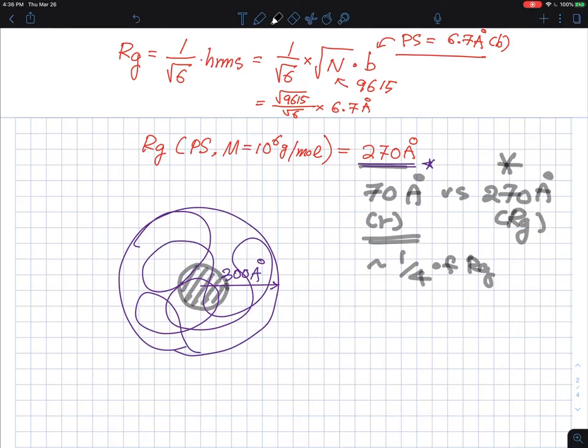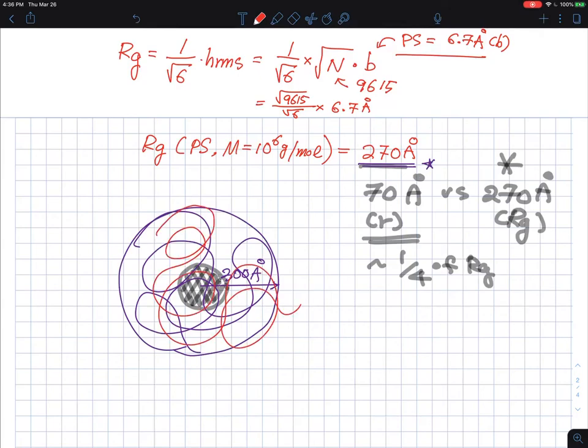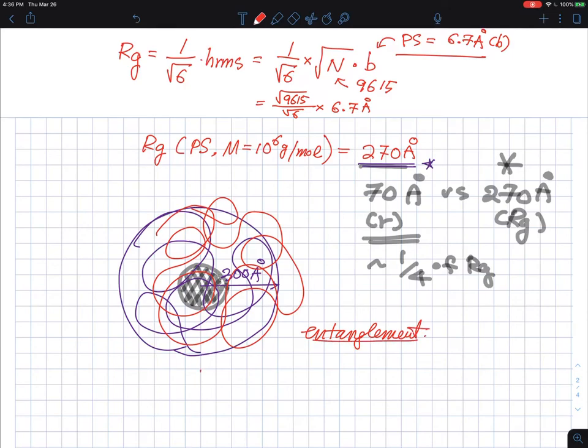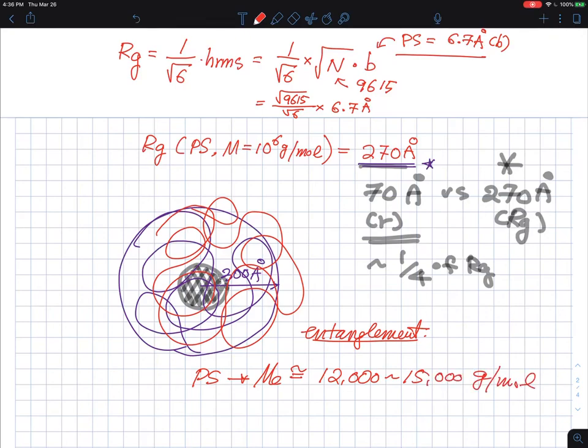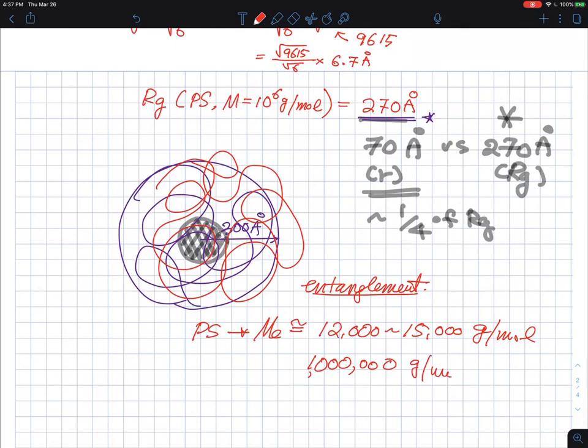What this means is there is quite an overlap between polymer chains, shown by the purple line representing the actual polymer chain extending far beyond the dense sphere. That overlap causes entanglement. For polystyrene, the entanglement molecular weight is about 12,000 to 15,000 g/mol. So at 10⁶ g/mol, you have many entanglements per chain — something like 30 entanglements — making this a very large molecular weight system.